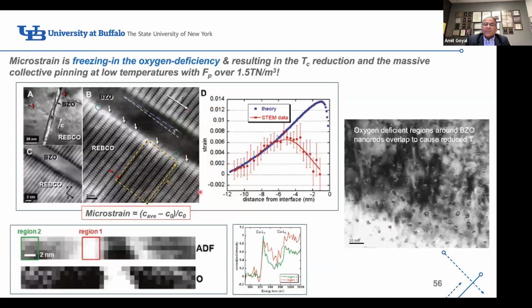So it turns out that you've got the Swiss cheese microstructure. Now you can draw a circle around each of these nanocolumns where the transition temperature is decreased and you have some oxygen point defects. I won't go through all of these details, but we've actually measured the microstrain locally, and that is plotted here from an individual nanocolumn and a finite element calculation.